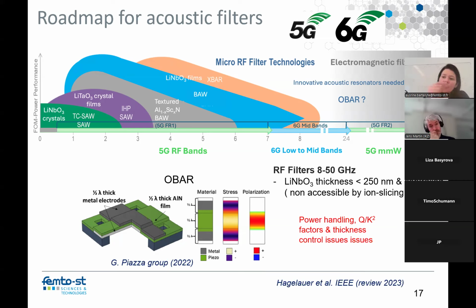So it was a limitation for aluminum nitride, until in 2009 we found that it's possible to dope with scandium. Doping with scandium helped to increase the electromechanical coupling of these films, which is done just by sputtering. And now, basically, we can go to 6 or 7 gigahertz. Qualcomm announced 7 gigahertz on aluminum scandium nitride films in the bulk devices. So it's just textured films grown by sputtering.